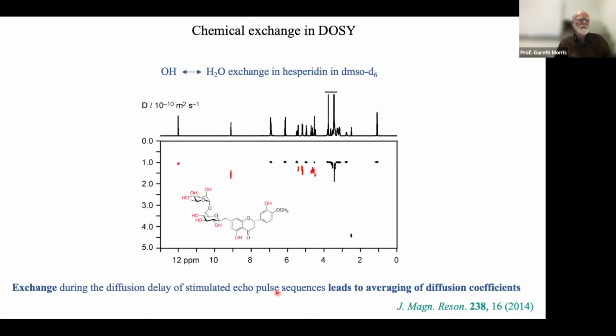And so if we look at this spectrum of hesperidin here, then we see that we've got a little bit of overlap with solvent there, as we expect. We see that all the CH signals give us very nicely lined up diffusion coefficient peaks, but the OH peaks are all at higher diffusion coefficient than we expect. And what's happening is that the OHs are exchanging with the water. Water diffuses really fast. And so even relatively slow exchange gives us a measurable effect on the apparent diffusion coefficient. So chemical exchange can be a problem.